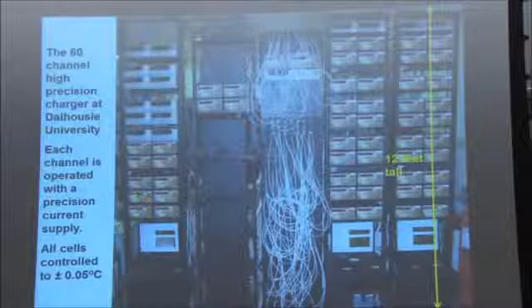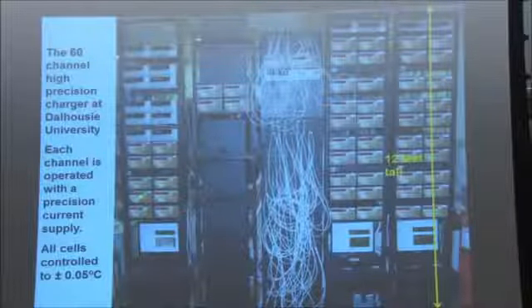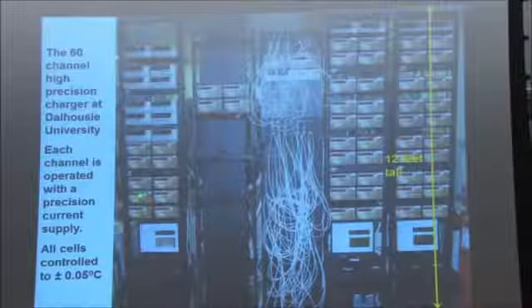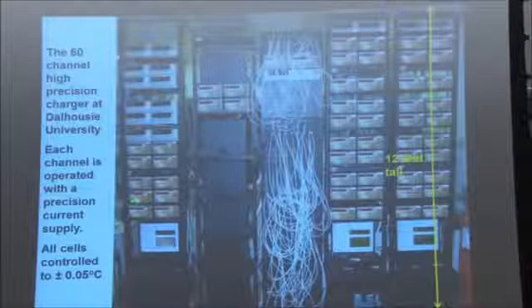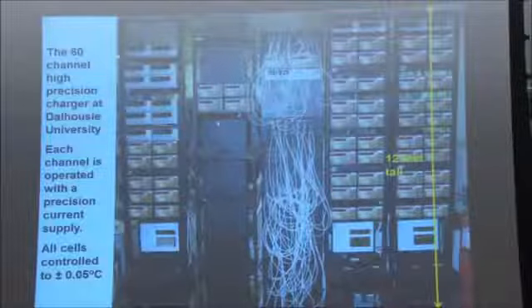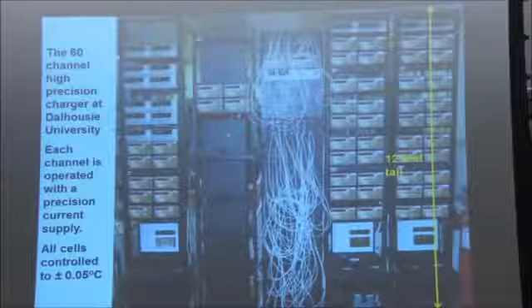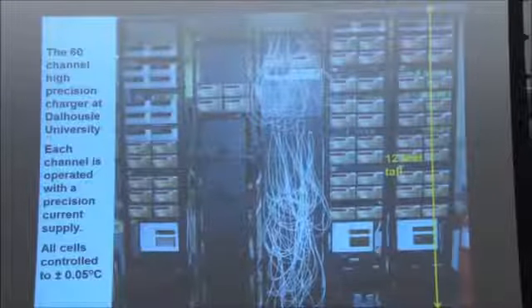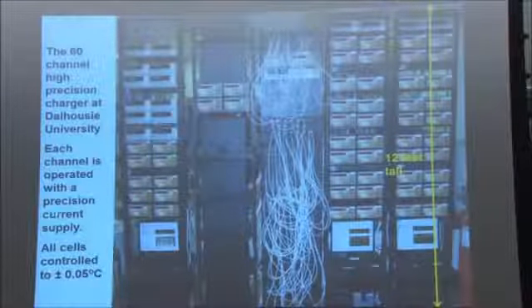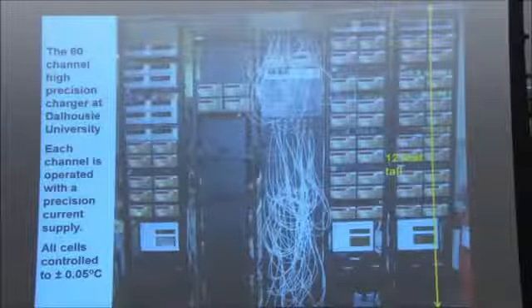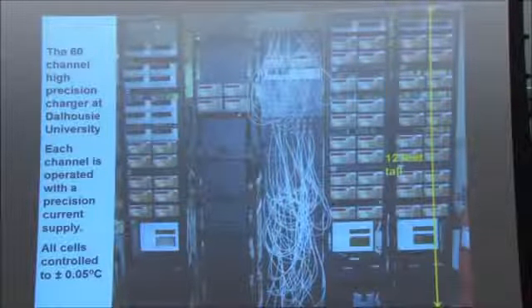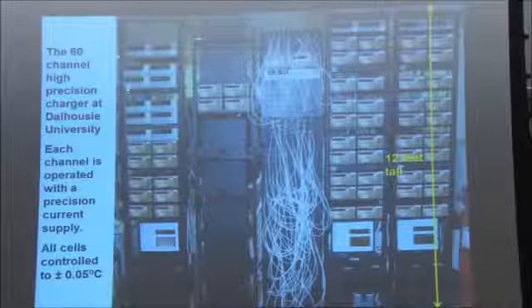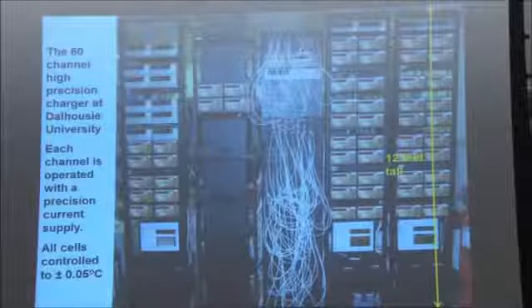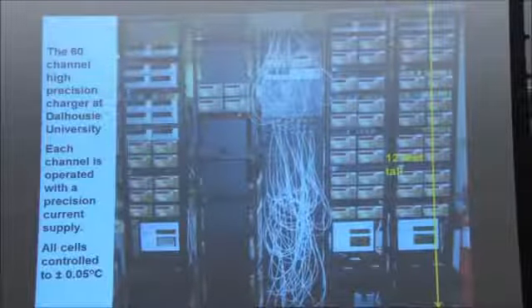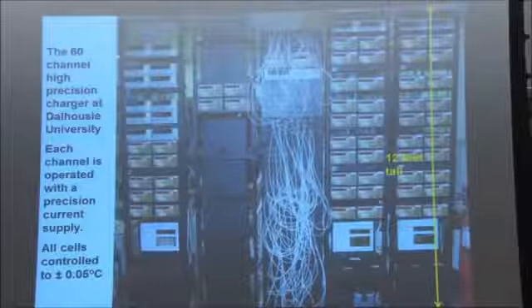Each of these brown boxes that you see is a precision current supply that supplies current with 5 digits of precision to a cell under test. And the cells under test are housed in these temperature-controlled boxes so that the temperature is very stable and you can measure the charge and discharge capacities very accurately. Everything's computer-controlled. The currents that these things output, even though they're very accurate and stable, we still pass those currents through precision resistors at the top of these racks and measure the voltage on the precision resistors to keep track of the current really well. And with this device, we can measure Coulombic efficiency very, very accurately.